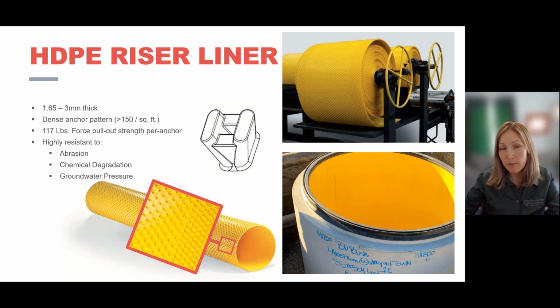Our perfect line manholes are manufactured with a 2 millimeter thickness. However, if need be, if you require higher back pressure, for some reason, if you have deep installation with high groundwater, we can manufacture it with a 3 millimeter or higher thicker liner.